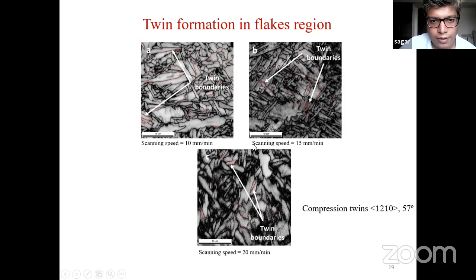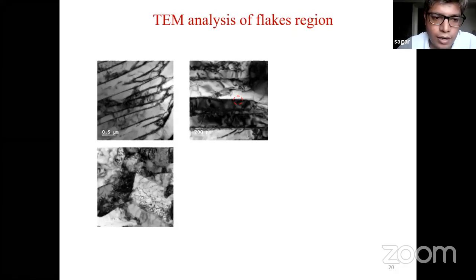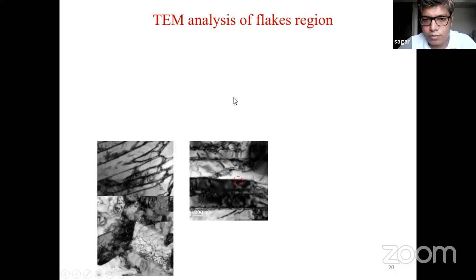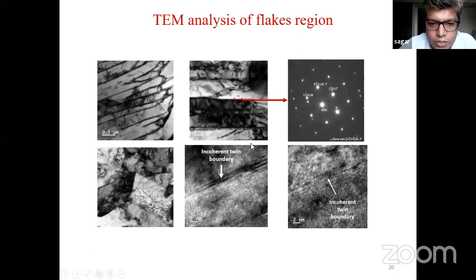Let's go ahead with the TEM analysis of those regions. You could see in earlier slides there were so many black points in the EBSD scan, mostly at the region where the laser has affected the material drastically. So we did the TEM analysis of this. These are nothing but the twins. Here also, with TEM analysis, we were able to find the twin formation. The twins we could see in EBSD analysis are reflected over here. Even at the atomic level you could see the twin formation.